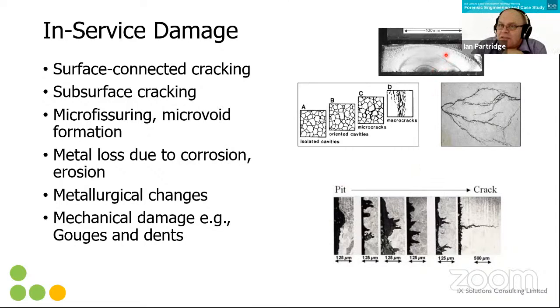So here you can see fatigue, which has a very classic failure face, where you can see the initiation point, and then as the crack slowly extends through the thickness, a bit like a tree ring. So if you cut a tree, you'll see rings, and you can see what are called beach marks. These normally are associated with something during operation, so it could be a shutdown.